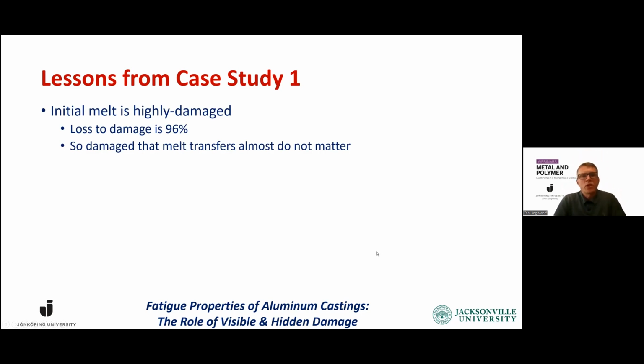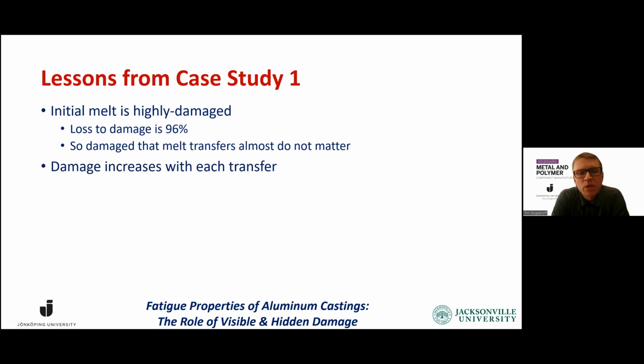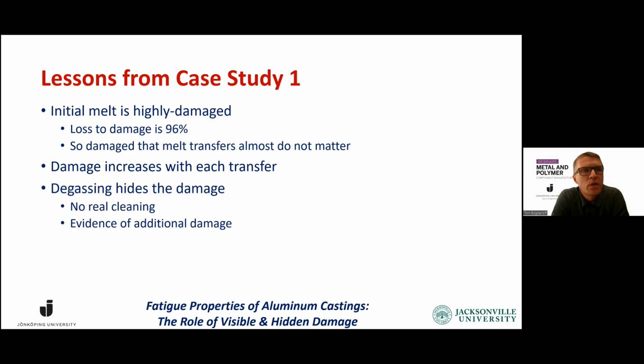So the damage of the melt transfer, it will not matter at all. The damage increases a little bit with each transfer. The degassing in this case is only hiding the damage with actually no real cleaning. Yes, it reduced the hydrogen level to a small extent, but what we can see from the mechanical properties and the tensile test, we don't see any difference. So is it worth actually doing these steps in a foundry with this quality of the melt from the beginning?